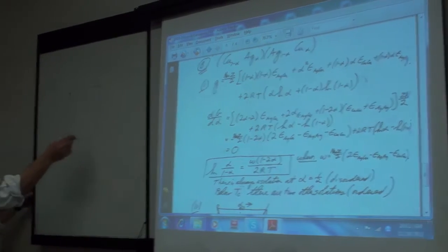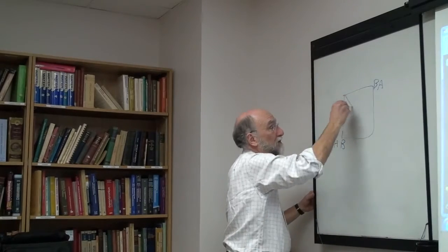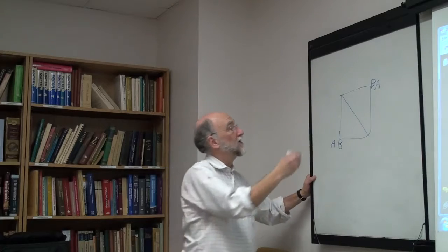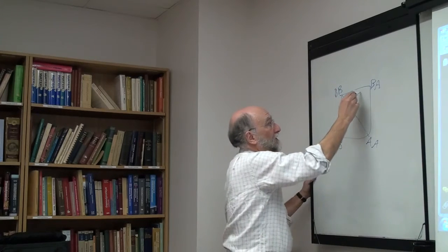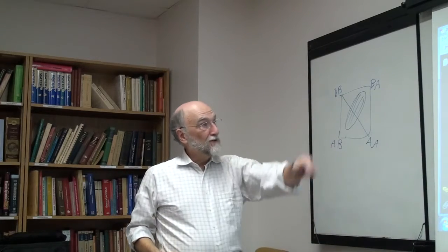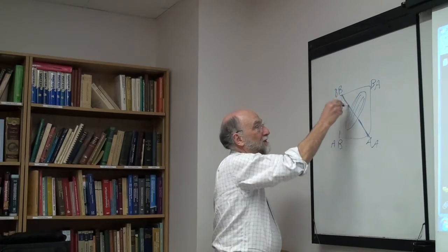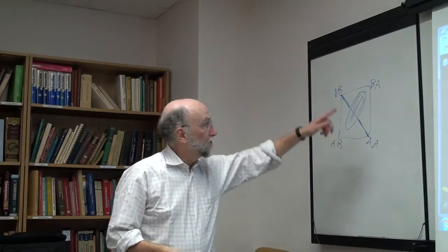So if you look at that as a reciprocal system, here you have AB, here you have BA, which is exactly the same thing as AB. There's no difference between the two sites. Here you would have AA and BB. And you actually get a miscibility gap along here. If you look at this as a reciprocal system, you're getting a miscibility gap. This is your disordered region. And this would be your ordered region along here as you're going through the entire system.